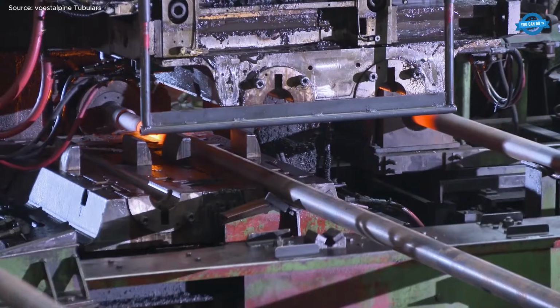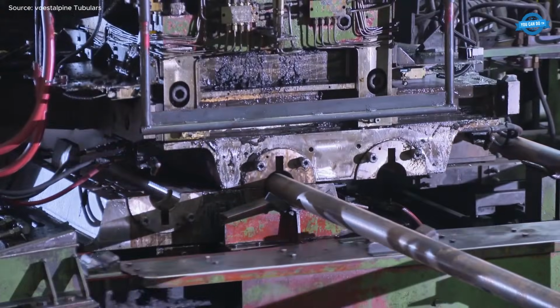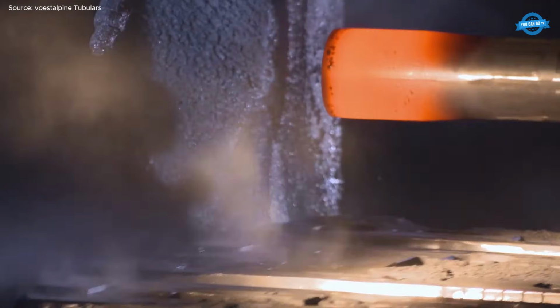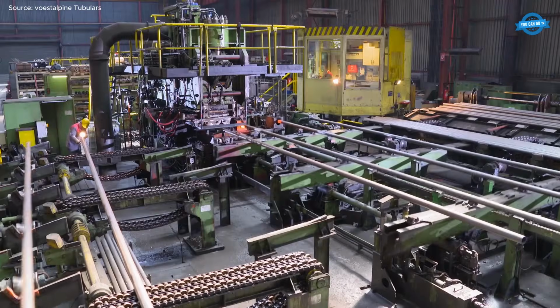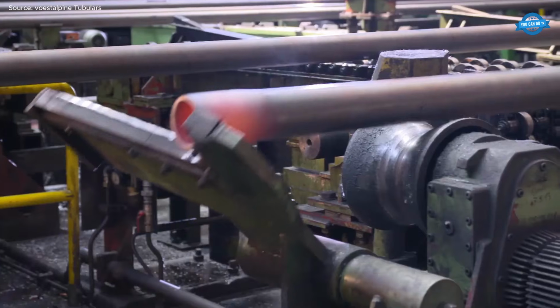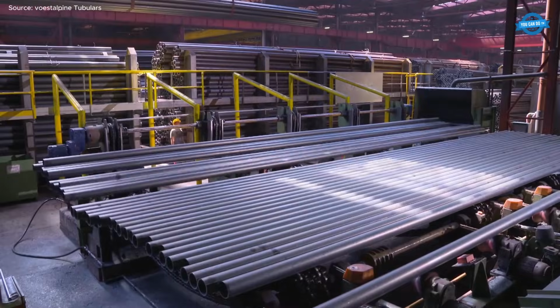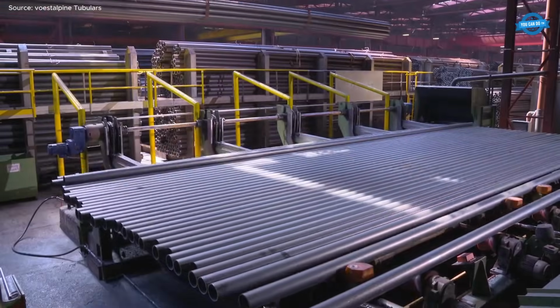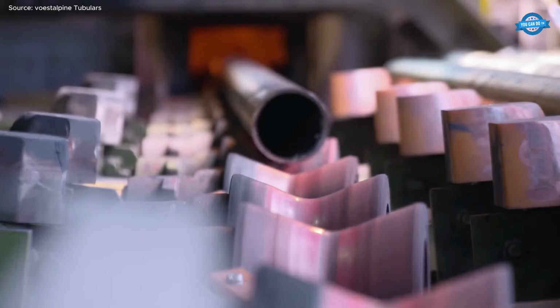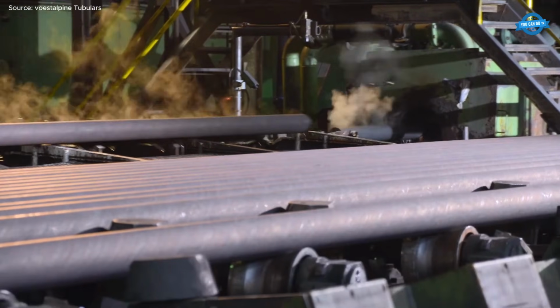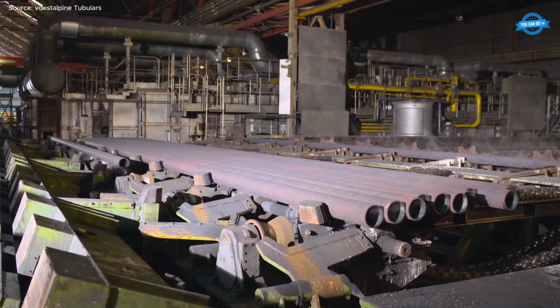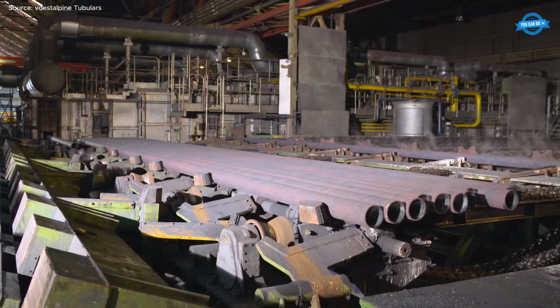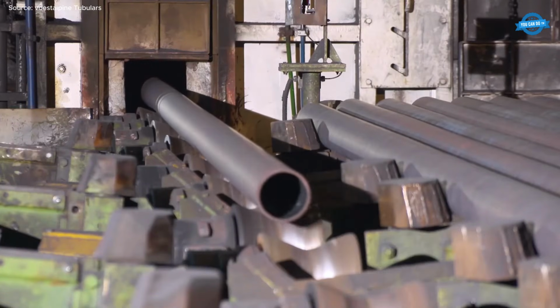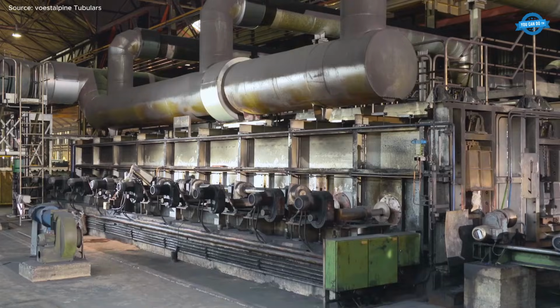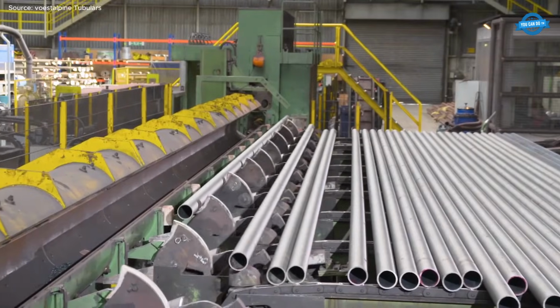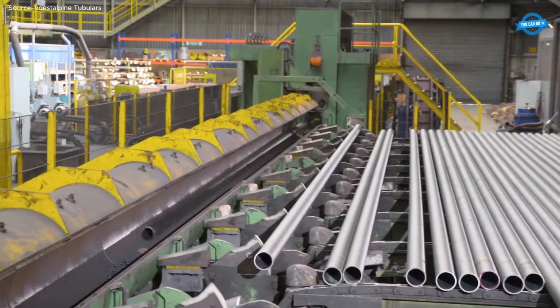In the austenitizing furnace, pipes are reheated so their microstructure transforms, enabling controlled quenching. Rapid cooling generates a hardened matrix, which is subsequently tempered at precisely regulated temperatures and dwell times to achieve the required steel grade. After heat treatment, rotary straightening machines restore tight linear tolerances.